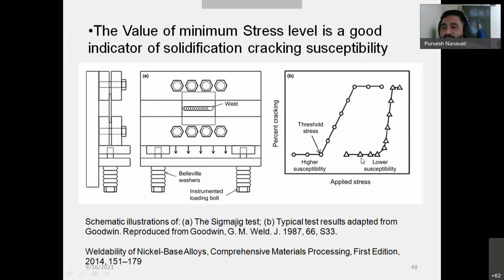Now you look at this curve. The curve at the bottom shows the lower susceptibility, but this one shows the higher susceptibility, where the percentage of cracking is very high, right? So this is percentage cracking versus applied stress. You start with the lower stress level and you come to the threshold stress limit, right? When you cross the threshold stress, you can judge the higher susceptibility. This is reproduced from a technical article on weldability of nickel-based alloys, and the sigma jig test is a very latest test in weldability testing of material.